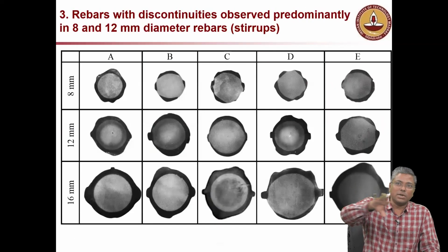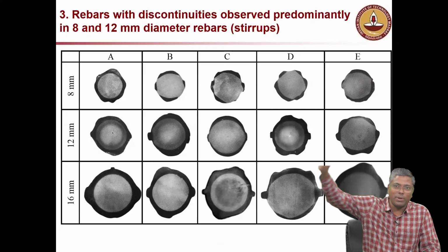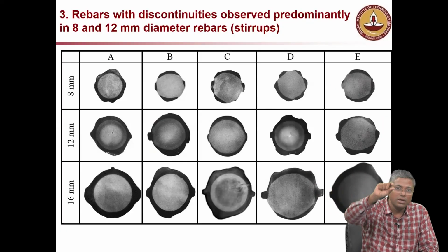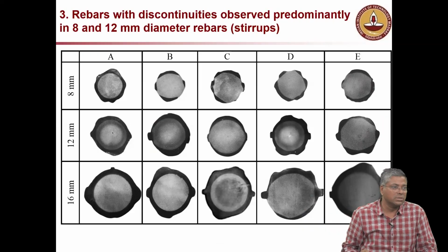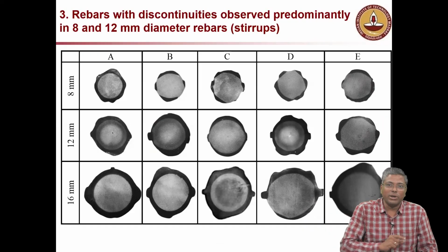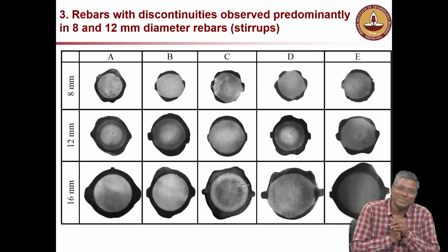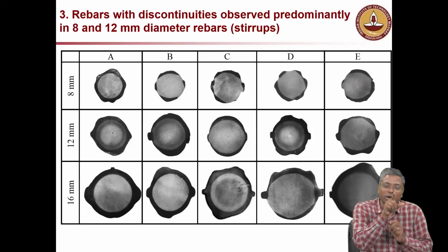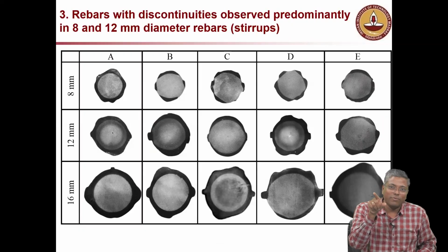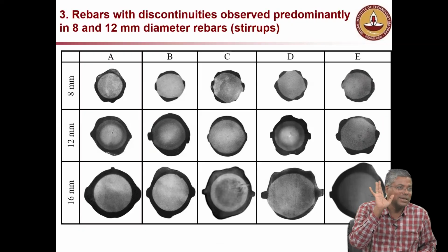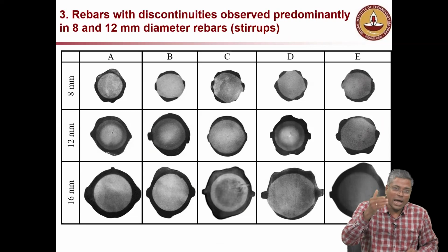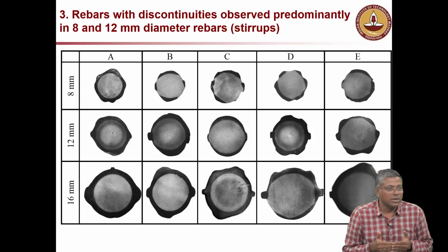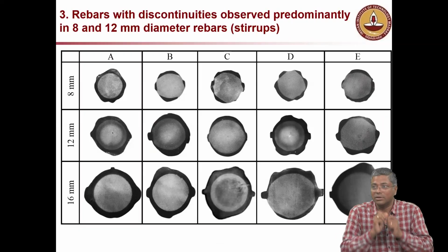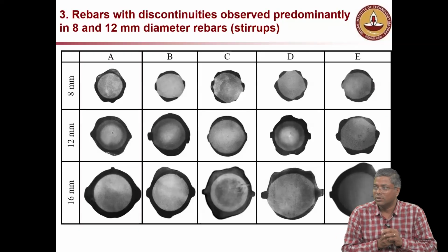So we tested many products. You can see on the top line, it's a small diameter bar. Then you have the larger diameter bars. Now, if you ask a company, they will show you the big one only. Look at the bottom one: 4 out of 5 are passing. You can see the ring is good. As the diameter is smaller, it's difficult to maintain or develop that ring during the quenching.